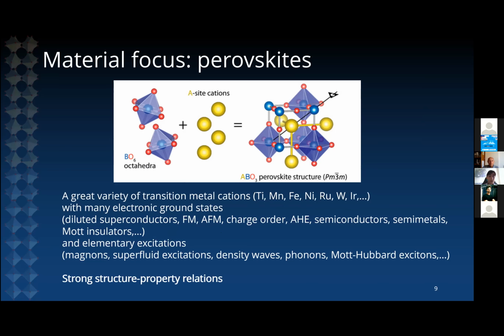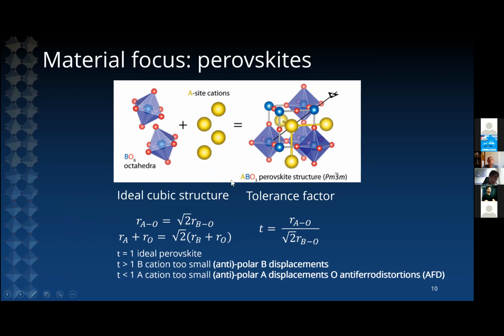And associated with these various ground states, there are many elementary excitations that we can use to manipulate the properties. So why is the perovskite structure so amenable to this type of manipulation of the electronic properties by the crystal lattice? The essential reason is that the perovskite is able to accommodate cations with various sizes by performing various types of structural distortions that lower the crystal symmetry from the high cubic phase to various low symmetry phases. And so depending on the type of cations that you want to incorporate, you can have a cation that is either too small to realize a cubic crystal structure.